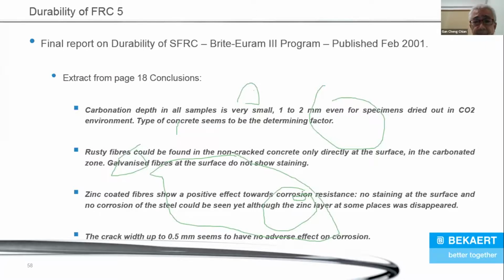It is an aesthetic problem. So we can even say that we increased the thickness of the segment to 202 millimeter just to take care of the carbonation. Rusty fibers could be found in the non-cracked concrete only directly at the surface in the carbonated zone. Galvanized fibers at the surface do not show staining. Again, fibers only stain on the surface. It's non-structural, it's an aesthetic problem.